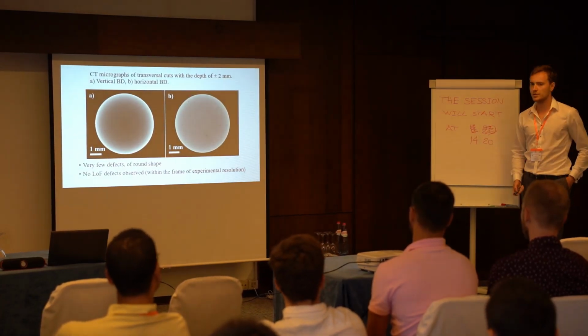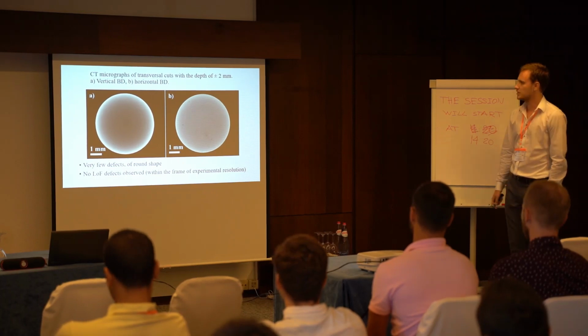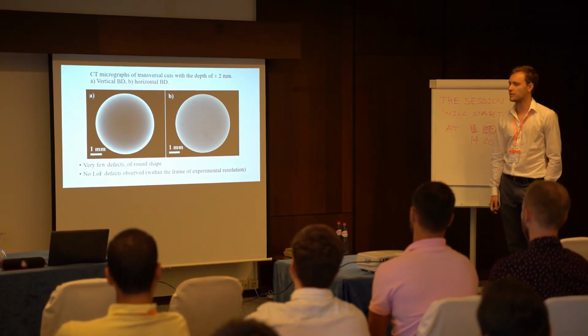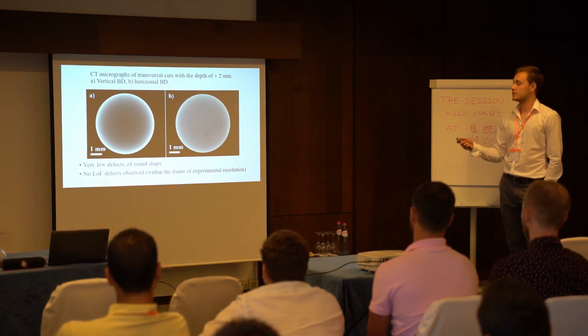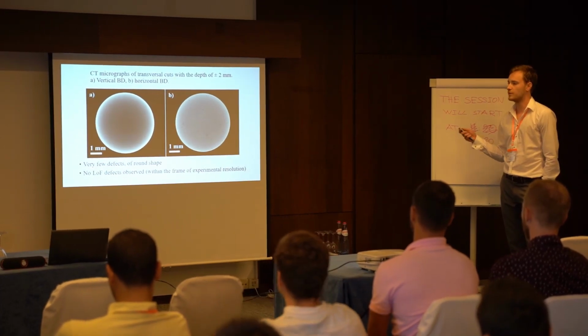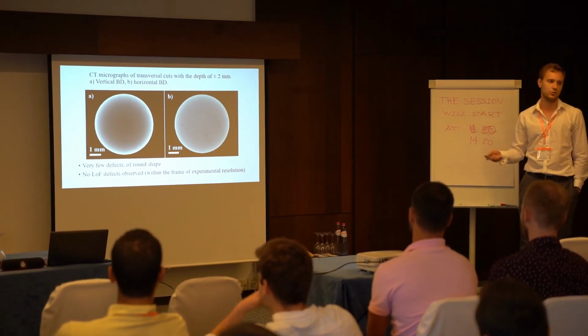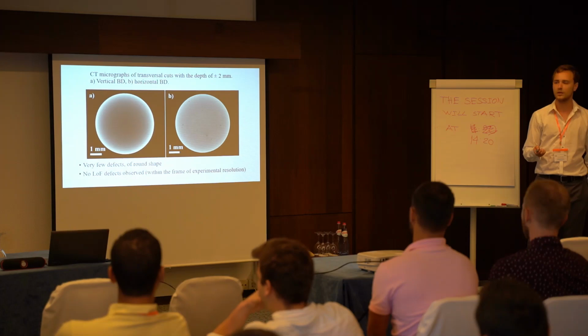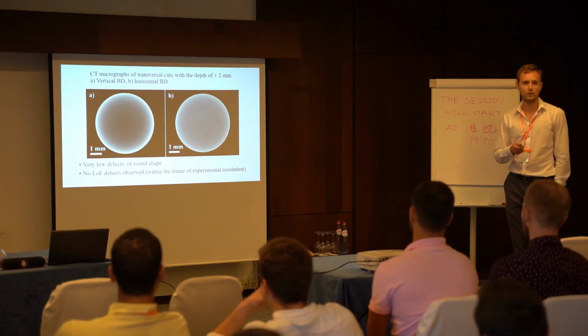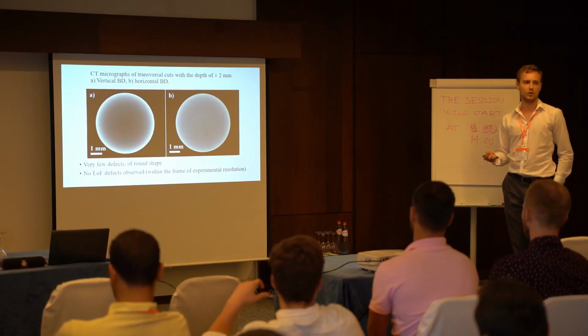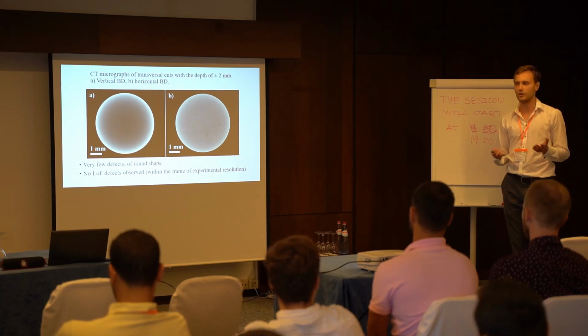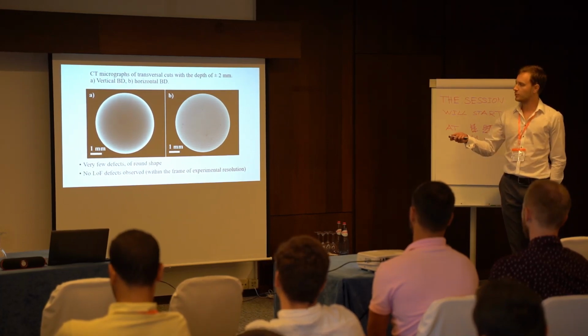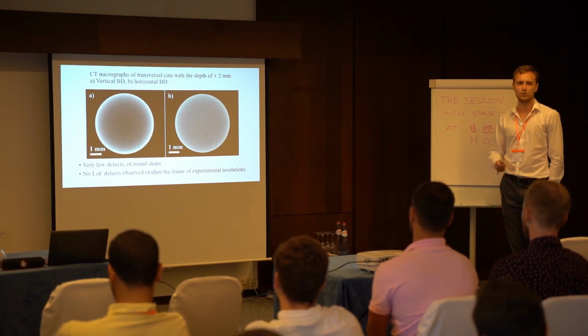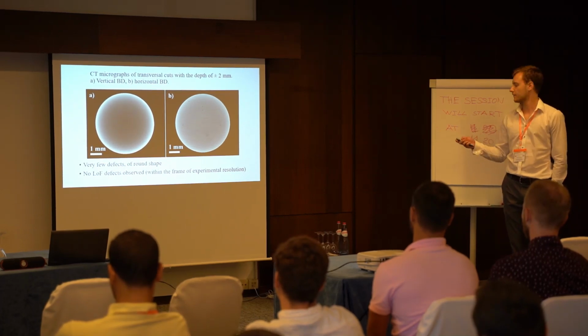So, to the actual results, now let's take a look at these CT scans to see what the defects were like. Interestingly, we found no lack of fusion defects within the experimental resolution, which was around 5 microns. So if there were any smaller, we didn't see that. Probably not, since lack of fusion defects are usually quite large. There were just a few round defects which are supposed not to be as bad, let's say.